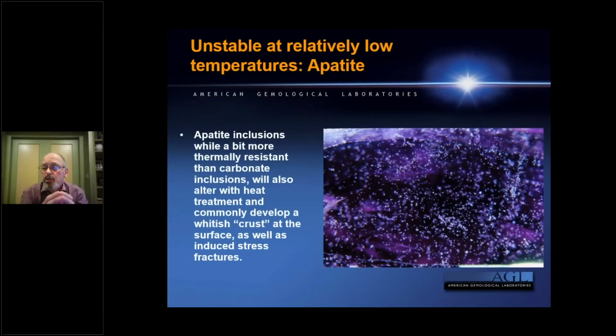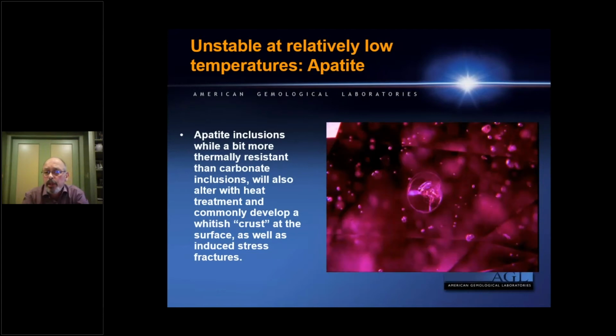When we talk about mineral inclusions that are more thermally sensitive, I use here apatite inclusions, calcite, micas, things like pyrrhotite and so on. This inclusion scene that you see is a Madagascar purple sapphire or color change sapphire. It's populated with a bunch of mineral grains like most of you should be familiar with in Madagascar stones. And at relatively low temperature heating, you can see from the background, the color was very, very effectively changed. And here we had a crystal of apatite, which a discoid or atoll type of stress fracture took place surrounding this stone. But if you also look, the whole area, let me try to point to the camera.